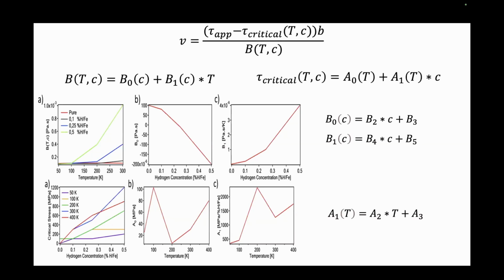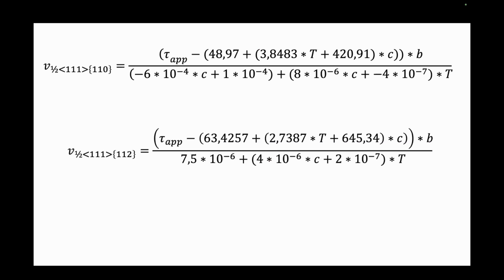How about the critical stress? Again, once you plot the critical stress as a function of concentration, you get a line equation, A0T plus A1T. Once you plot A0 as a function of temperature, we didn't get a line equation, therefore we assume this is a constant and take the average value for A0. For A1T, we assumed it's a linear line and we performed linear regression, so A1T is equal to A2T plus A3. Then we got the numbers and came up with the phenomenological mobility laws for 110 and 112. The Burgers vector is always 111 for BCC. For FCC, it's 110 and the planes are 111, but for BCC the Burgers vector is 111 and we have 3 different planes.